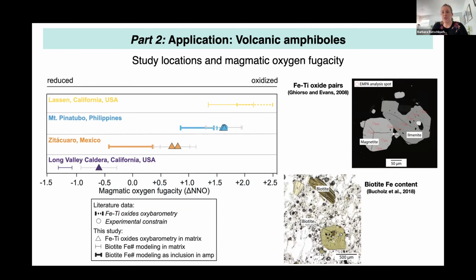And we can determine that by using different tools. One of the tools we used is looking at iron titanium oxide pairs. On the right, you can see a backscatter electron image of a magnetite and ilmenite pair. So you can use their composition to determine the magmatic oxygen fugacity. Another tool we used, which was actually developed by one of my co-authors, is looking at the iron content of a mineral called biotite. It usually co-crystallizes with amphibole in those magmas. And you can see a microscope image here on the bottom where a brown biotite is fully enclosed in an amphibole. So there's good evidence that they actually co-crystallized.